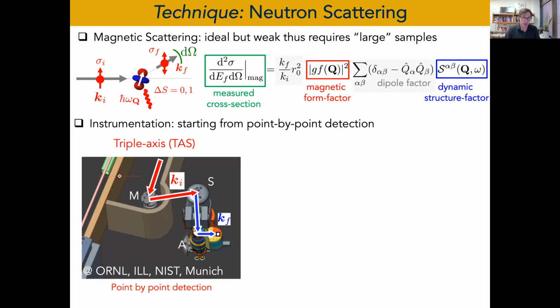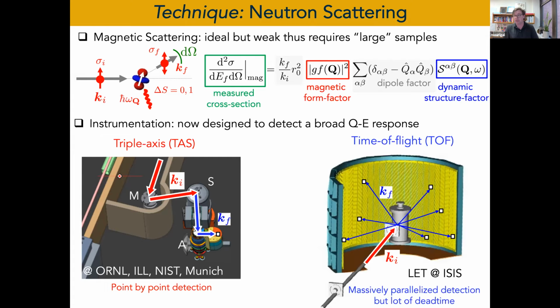And just a quick word that the techniques we use to do neutron scattering have evolved over time. And the venerable triple axis spectrometer, which was the way that inelastic scattering was discovered, you essentially measure your reciprocal space point by point by moving crystal analyzers or crystal monochromator in reciprocal space and the sample, exploring reciprocal space like this. So this is a point by point detection technique that may not be as efficient to map broad spectra or continuum spectra. So in the last 10 years, although this exists for a long time, the technique of time of flight spectroscopy has really blossomed. And this is now the main technique we actually use to explore new materials.